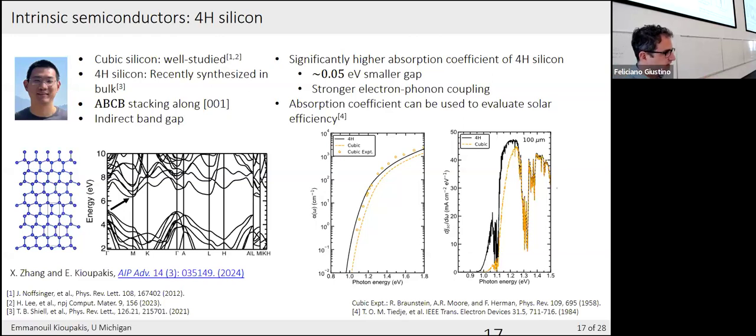And yeah, the band structure can be in principle completely different. So we do see a small reduction of the band gap, but we also do see a stronger absorption because of the broken symmetry. Light gets absorbed but phonons help break the symmetry, and that's what allows the transition across the band gap. So anything that breaks the symmetry helps the absorption. Potentially it could hurt the conductivity, but the absorption definitely gets improved.